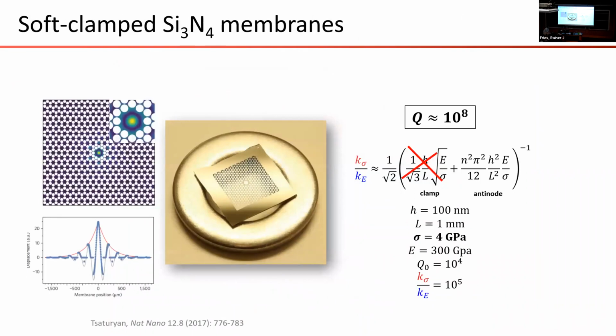So I just want to say you can do the same thing with membranes. Membranes are actually a big thing in optomechanics because they have larger surface areas. You can couple them to optical fields. A little harder to model, but you can achieve the same effects and get really high quality factors with basically two-dimensional strings as you would with one-dimensional strings. Something that's one of the bad things, if you will, about these really small mechanical oscillators is that how do you reflect light off of an object with dimensions smaller than the wavelength of light? It's helpful to have a two-dimensional object so that only one of the dimensions is smaller than the wavelength of light in order to get a strong optomechanical interaction. So actually, although the formalism for understanding this dissipation dilution is much easier for a one-dimensional string, most of the innovation in high-Q nanomechanics has started in membranes and got transferred to strings just because membranes are easier to couple to, say, microwave circuits and optical cavities.